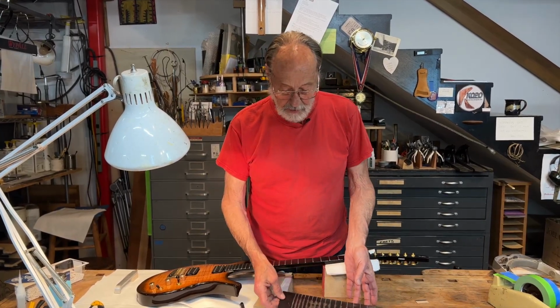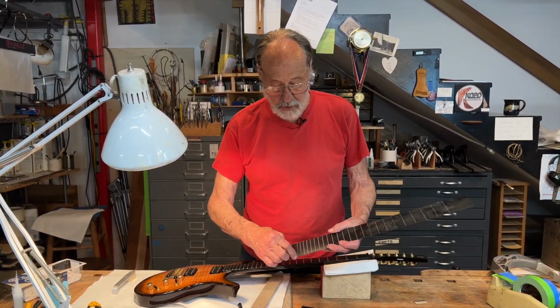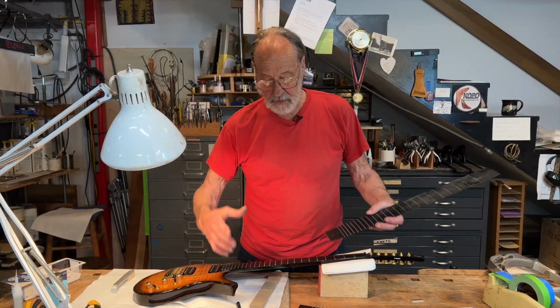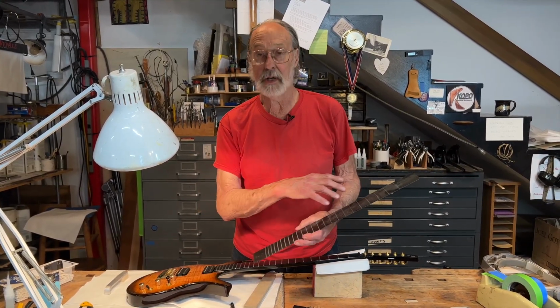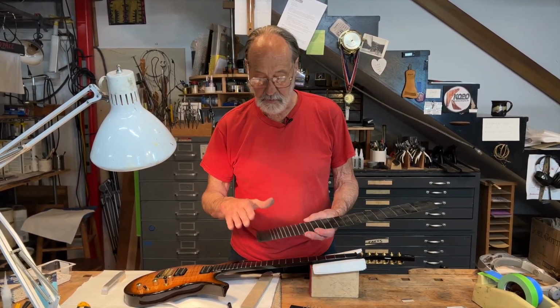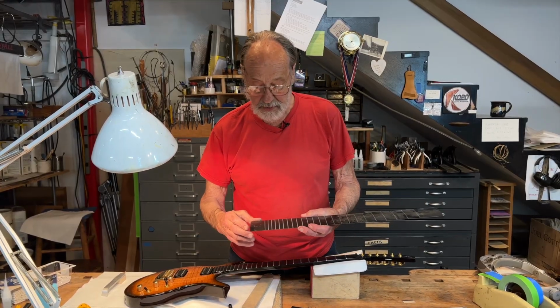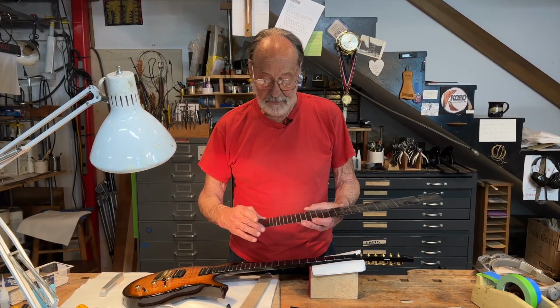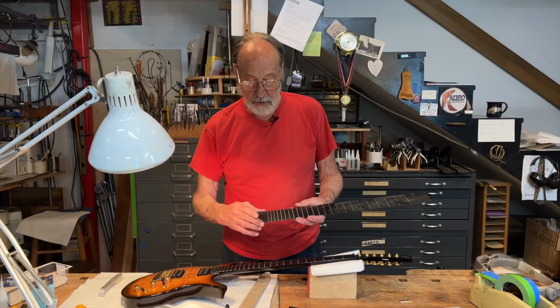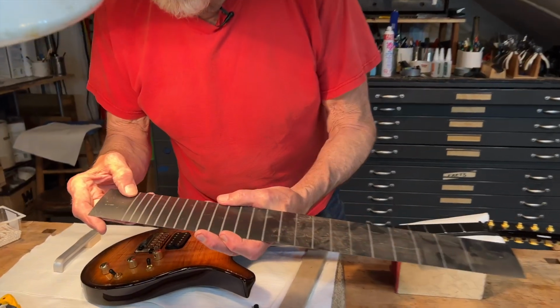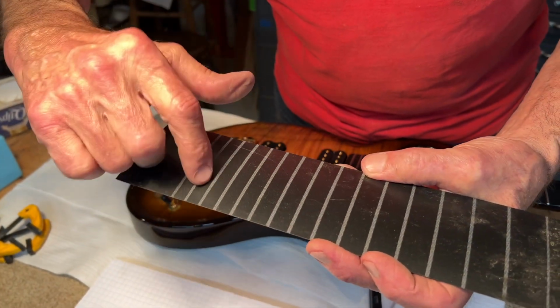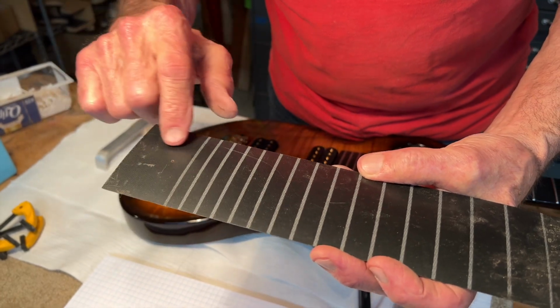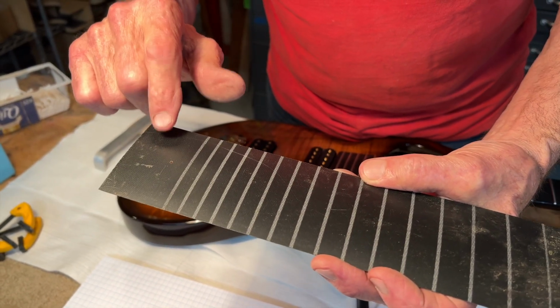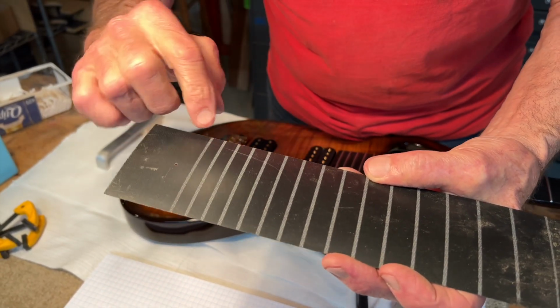So the accelerator would go on the fingerboard, the glue would go on the fret, and there was a crazy fixture that made sure everything was in the right place and all the frets were straight and correctly spaced, and clamped down with quite a lot of force. Now, you can see on this fingerboard that where the fret is going to glue is cleaned off. The adhesive in the fiberglass cloth is cleaned off.